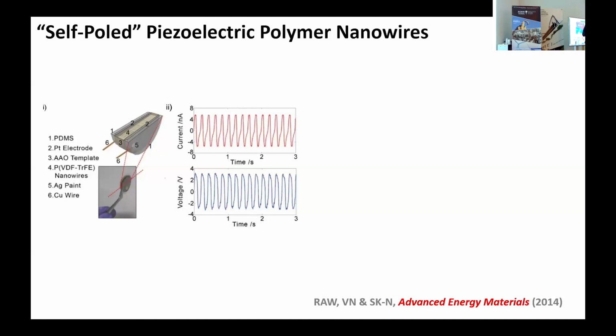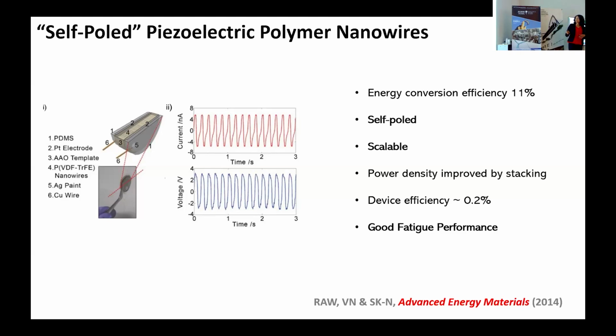Of course, these experiments were done with a shaker. I didn't have the student tapping around all day. So this is a shaker where you can control the amplitude with which you're applying pressure and the frequency as well. And it works out really well. What we found is that if you look at the energy conversion efficiency of this material here, it's about 11%. And to put that into perspective, if you do the same experiment with just a film of PVDF or bulk PVDF, that number is about 0.5%. So this is already quite a large improvement. But the most remarkable feature that we found is that these nanowires are self-poled.